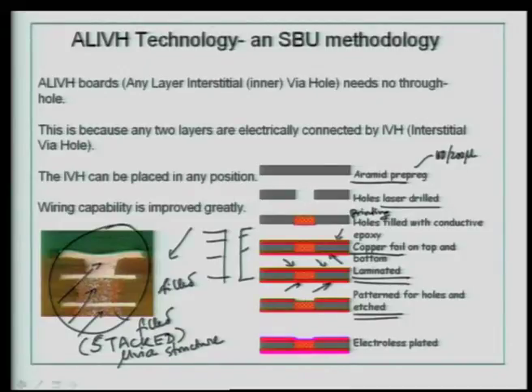So, you can remove the copper here. You can create a pattern as you have seen here, and then you can create a microvia again by using your print and by using your photovia methodology. You can open up a microvia, or you can also use laser drilling additionally to open up the copper and then create a microvia structure. So, layer by layer you can build up. Okay. But the essential process is that you get the ready made available pre-preg materials using aramid. They are of standard thickness, but you eliminate mechanical drilling here totally. You can align these microvias like here and stack them to get a comparatively through hole kind of construction, and you can expect, if your process is well established, a very good reliability even in these stacked microvias.